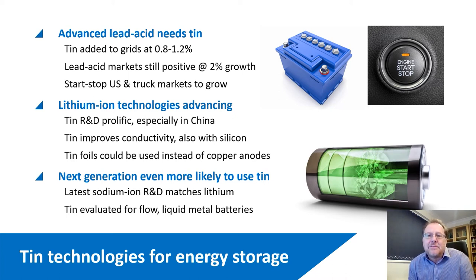In fact, tin is already benefiting from this because we know that a small amount of tin is used in lead acid batteries here, about 0.8 to 1.2% in the grids of batteries. And those lead acid markets are still growing and expected to grow still at about 2% indefinitely, even though electric vehicles are coming along and lithium ion too. In fact, tin is already benefiting specifically because of start-stop technology. So start-stop vehicles, which are the main production now, especially in Europe, require high-performance lead-acid batteries, and those high-performance batteries are the ones which have extra tin.